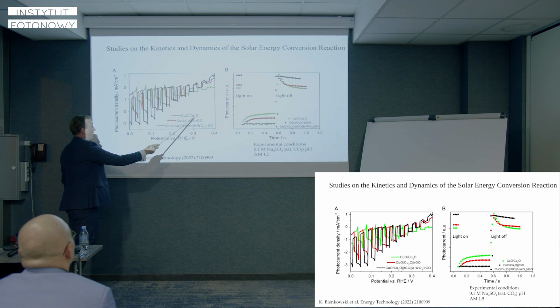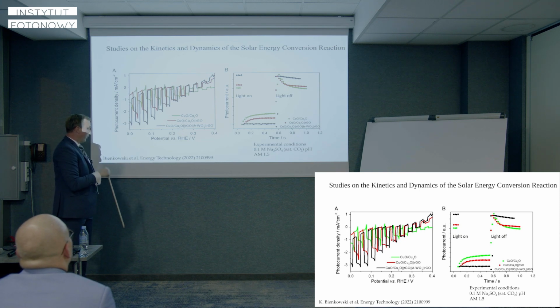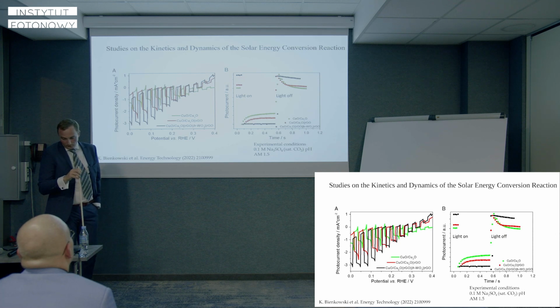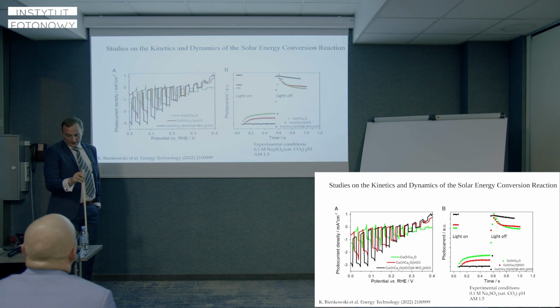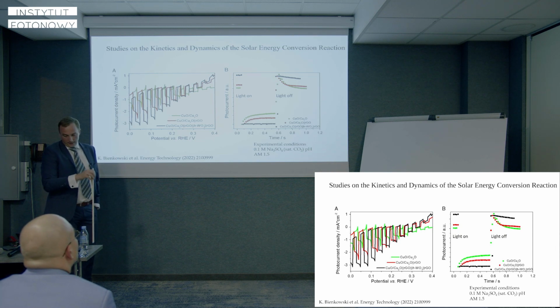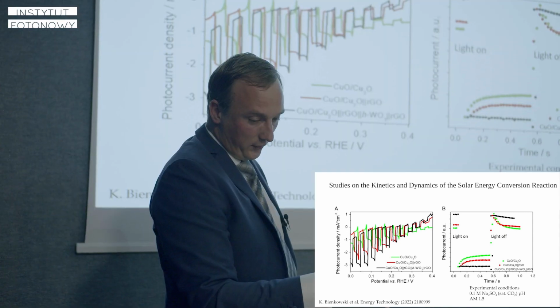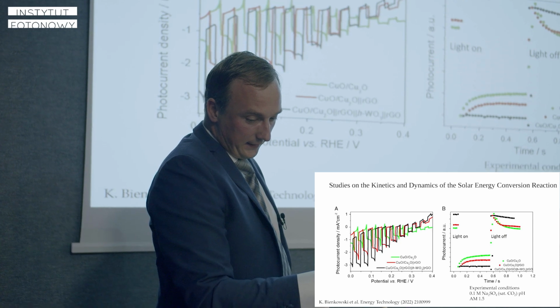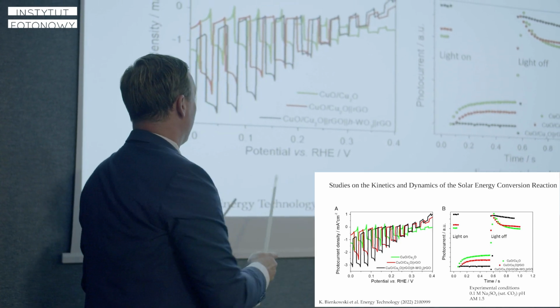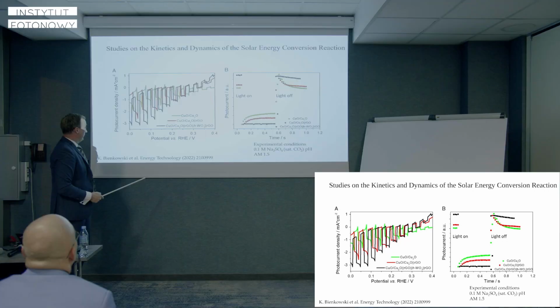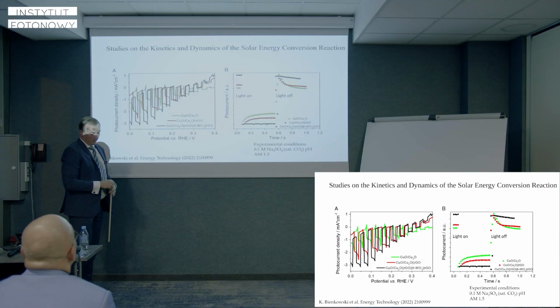So our final electrode, which is the black one, has the smallest recombination photocurrents, compared with the pure system, which is copper-copper oxide, and copper-1, copper-2 oxide with only reduced graphene oxide. Moreover, the charge transfer resistance at the working electrode-electrolyte interface was significantly reduced in our final system, with a significant increase in the efficiency of energy conversion, and the photocurrent for this final electrode was the highest.